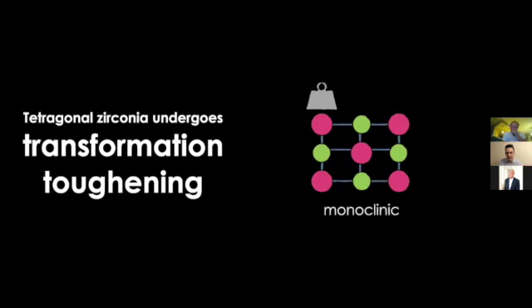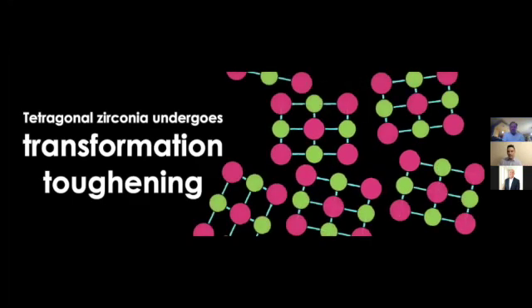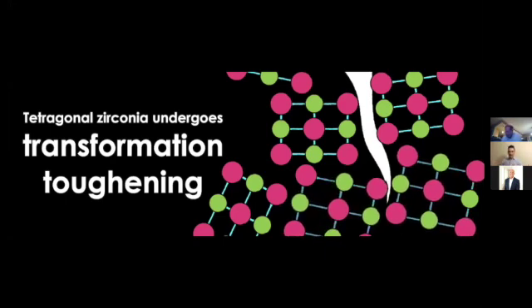So they expand, they get 3 to 5% bigger. So if you've got a bunch of these tetragonal crystals in your zirconia crown and they're all up next to each other, and then you do something like grind on that crown, or you sandblast it, or the patient bites on it and a crack is started. When that crack is started, it causes local stress on these tetragonal zirconia grains, and in response, they'll transform and they get bigger. And what happens when they get bigger is they compress that crack and they stop it from growing and getting any larger. And so I call that the magic of zirconia.